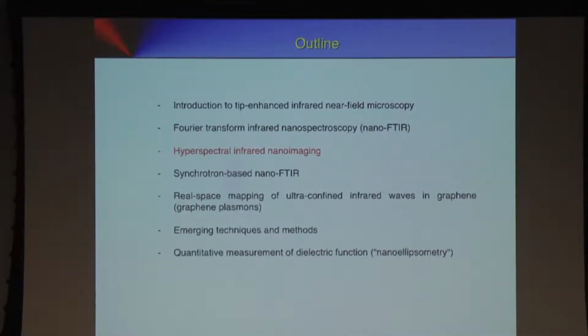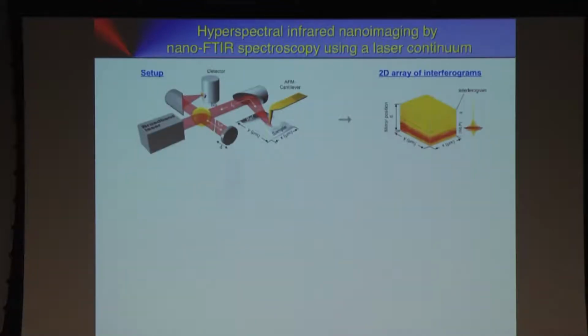All right, so that was point spectroscopy combined with imaging. Of course, the best we could do is getting a spectrum at each pixel. And this is what is done in far-field methods. It's called hyperspectral imaging. You also do that with synchrotron radiation. And this is what we wanted to try. But we should keep in mind that the spectrum takes many minutes. So that was a big challenge for us. And we have only a limited spectral bandwidth with our laser. Nevertheless, we tried it because we wanted to see, is it feasible at all with current technology?